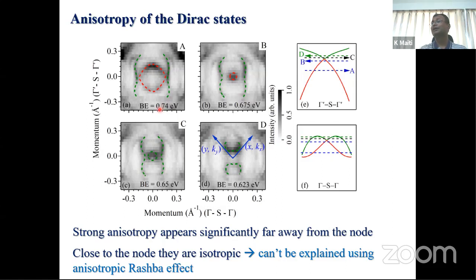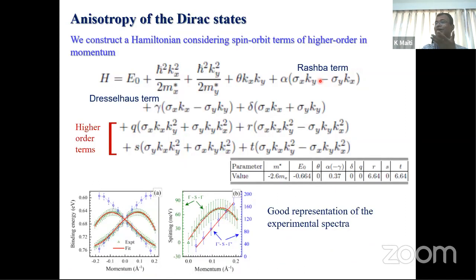So if you have isotropy close to the node and anisotropy far away, this anisotropic Rashba coupling cannot really explain this behavior. So what we have done is construct a Hamiltonian based on this observation, where we see that if you use higher order terms, this is a k dot p kind of methodology that we have used. Where 0 is your S point and any deviation from 0 is the kx and ky. Okay. So if you include these higher order terms, you can exactly capture the band dispersion that we have found, and the corresponding terms that you can see, this R and S, give you the higher order terms, which are quite significant.